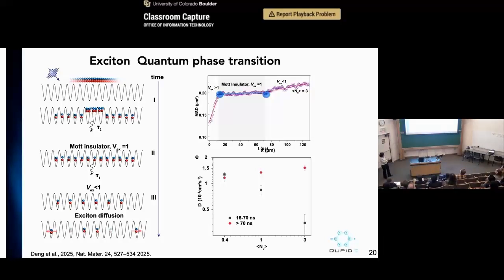And then if you wait long enough, because these excitons have a lifetime of about 150 nanoseconds, if you wait about 80 nanoseconds or so, you start to lose enough excitons so that your Mott state has a lot of defects in it, and then you start to resume this motion again. So you actually do see 2 phase transitions. One is when you form this Mott insulator state, and the other is the melting of this insulator state.